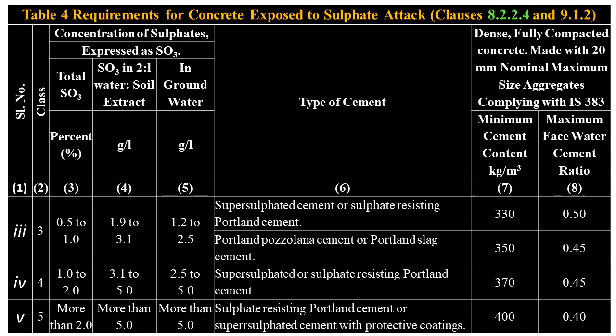Type of cements: sulfate-resisting Portland cement, or supersulfated cement with protective coatings. Minimum cement content, 400 kg per cubic meter. Maximum free water cement ratio, 0.4.